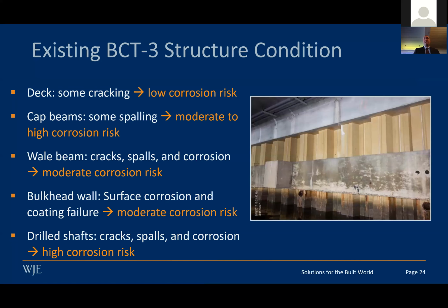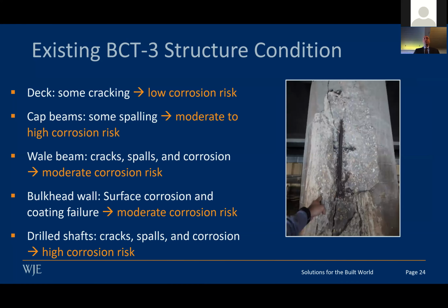The wale beam, as you see in this picture, had corrosion. I have a better picture later on, but beyond that, the bulkhead wall, these are all within the splash zone and see a lot of wetting and drying. And then finally, the drilled shafts, you can see the spall that was observed, a lot of risk for corrosion.